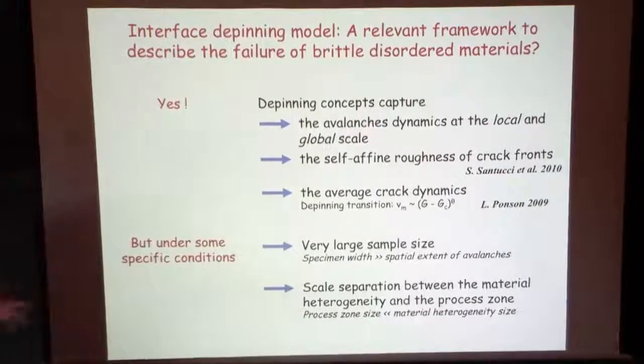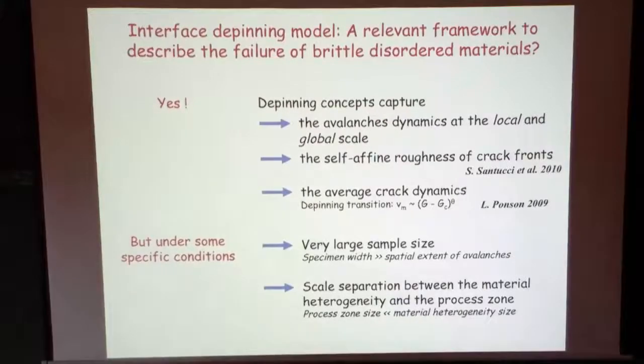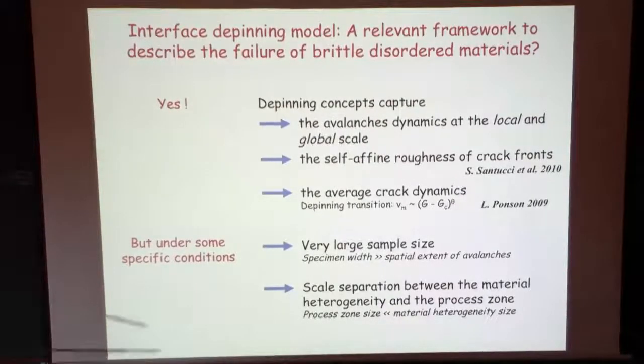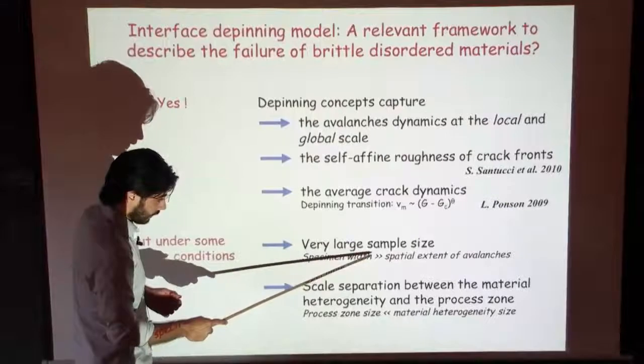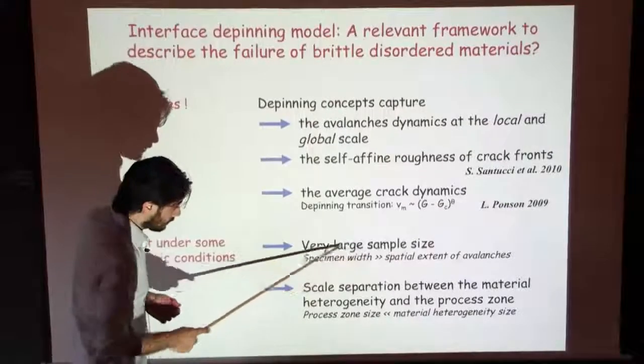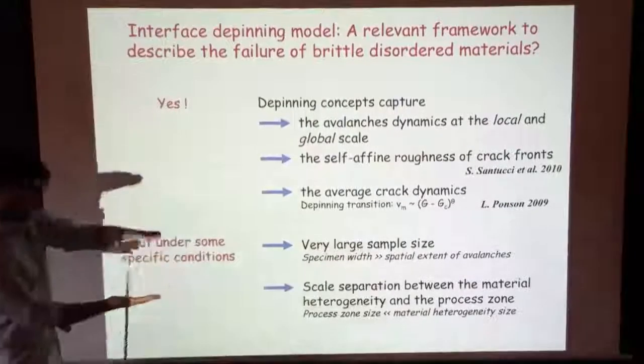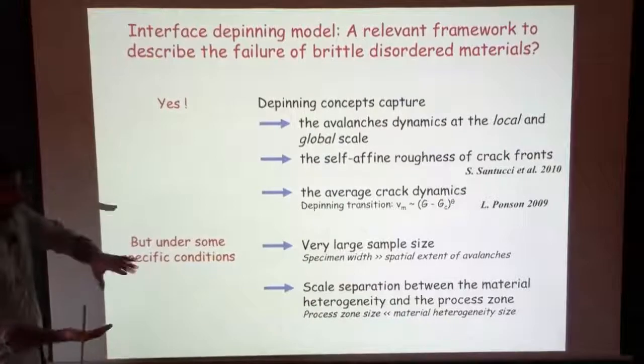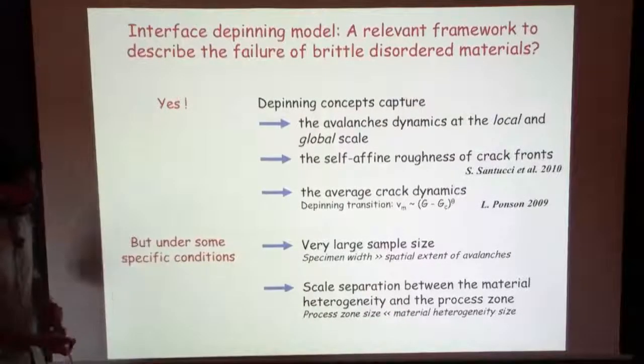A fracture takes place in a finite size sample, and so if you want at least to compare prediction with experiments, you need in particular to take specimen widths in this direction very large with respect to avalanche size. That's really a key point.